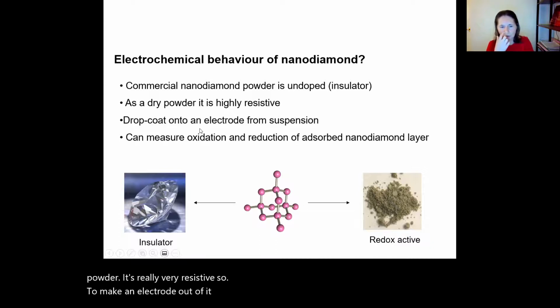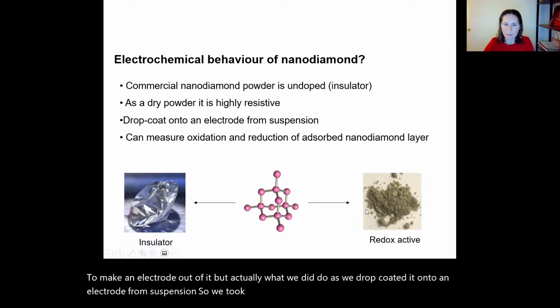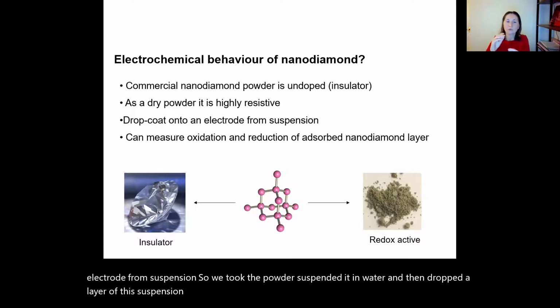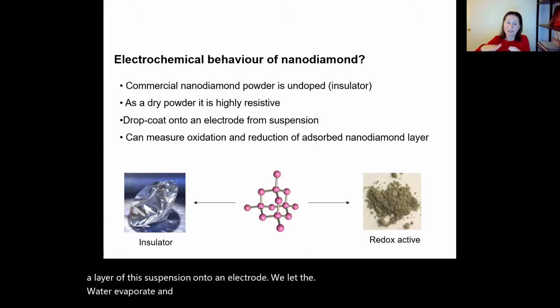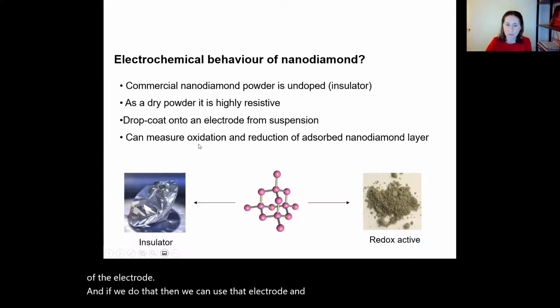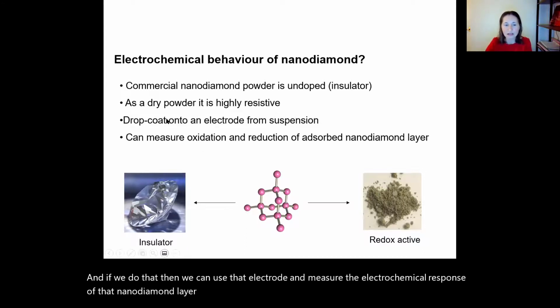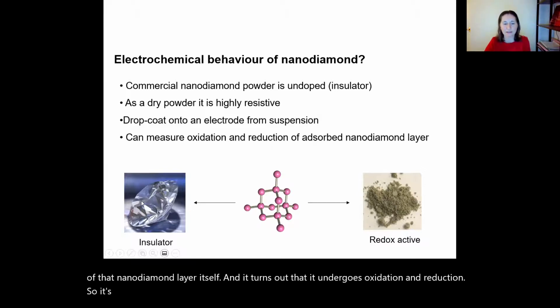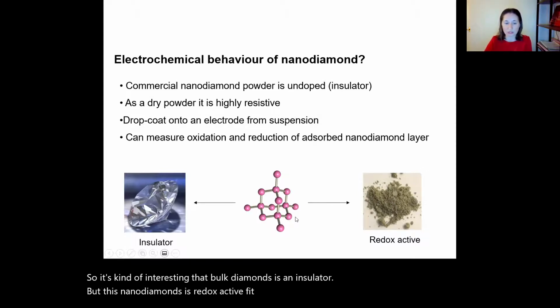But actually what we did do is we drop coated it onto an electrode from suspension. So we took the powder, suspended it in water, and then dropped a layer of this suspension onto an electrode. We let the water evaporate and you're left with a layer of the nano diamond that adheres to the surface of the electrode. And if we do that, then we can use that electrode and measure the electrochemical response of that nano diamond layer itself. And it turns out that it undergoes oxidation and reduction. So it's interesting that bulk diamond is an insulator, but this nano diamond is redox active. It has electrochemistry associated with it.